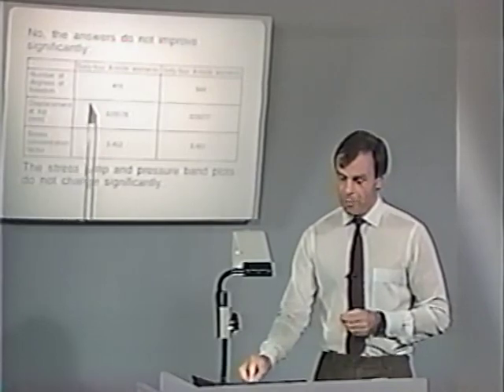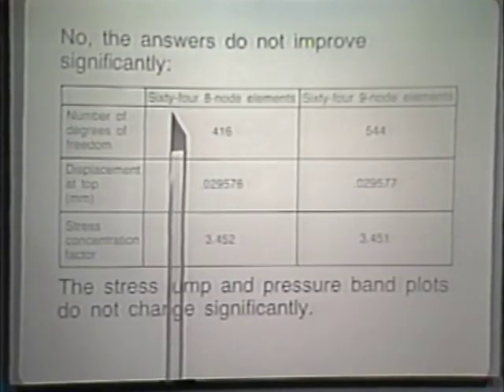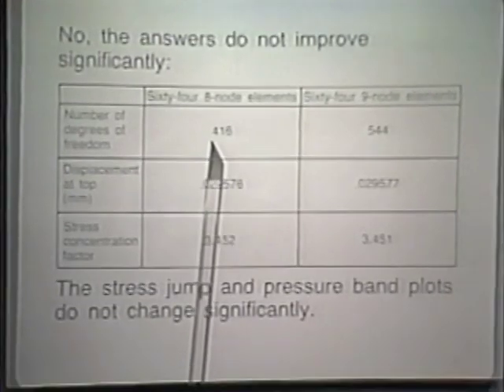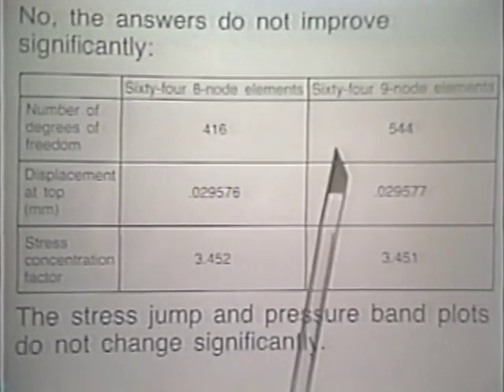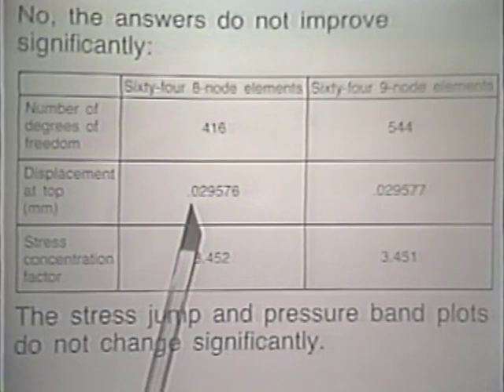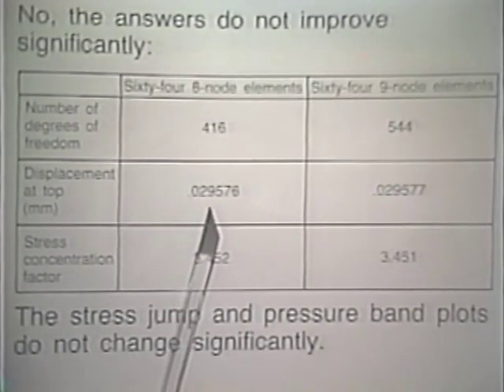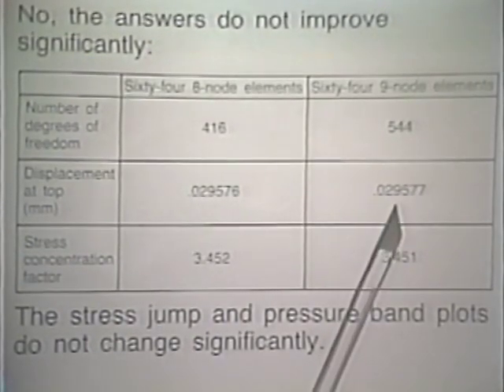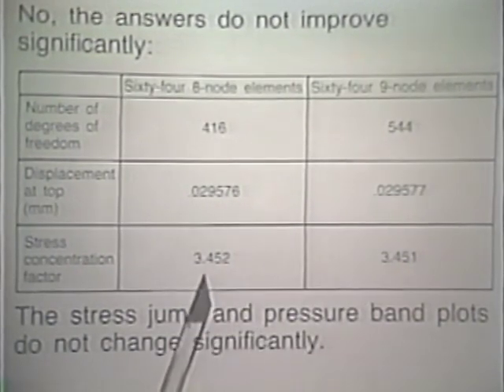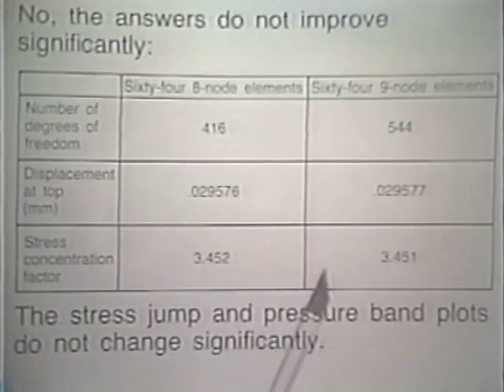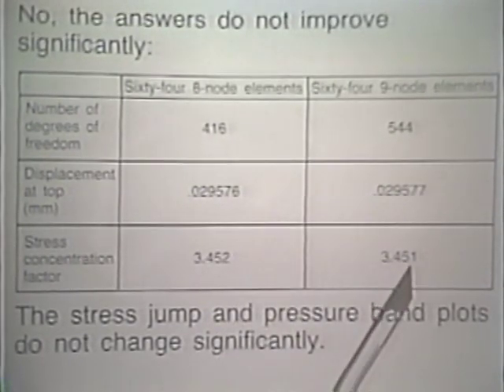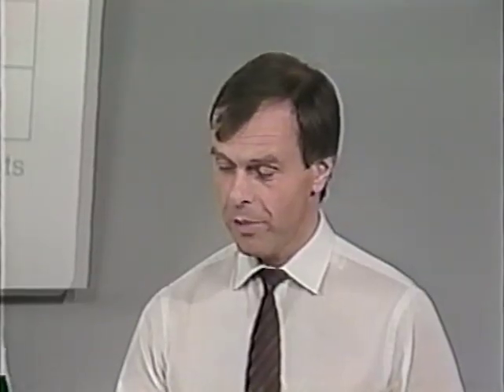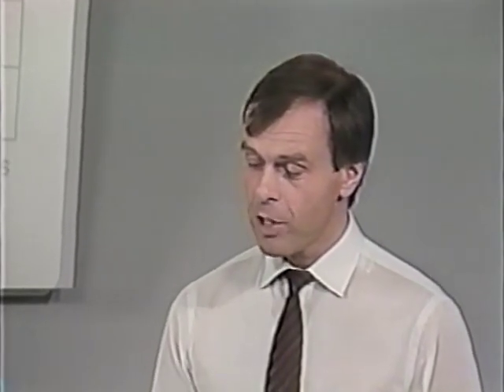If we look at this column here, let's look at the 64 8-node elements solution, in which case we had 416 degrees of freedom. With the 9-node elements, we will have 544 degrees of freedom. The displacements at the top are unchanged between the 8-node and 9-node element results. The stress concentration factor is very little affected here, only in the fourth digit, as a matter of fact. And the stress jump and pressure band plots do not change significantly either.